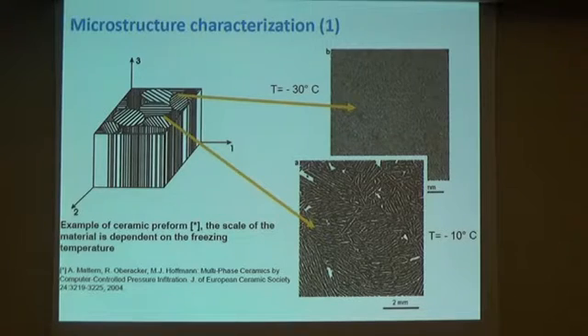But because the manufacturing and fabrication are driven by ice, the physics of ice, these composites exhibit very complex microstructure, hierarchical lamellar microstructure. So this is a schematic showing you what's going on here. We have domains in which metal and ceramic lamellae are parallel to each other, but these domains are oriented at certain angles to each other. And depending on the freezing temperature, we may have a fine microstructure or a coarser microstructure, and you can see from these photographs regions of parallel lamellae, and then lamellae at a different orientation in another area.